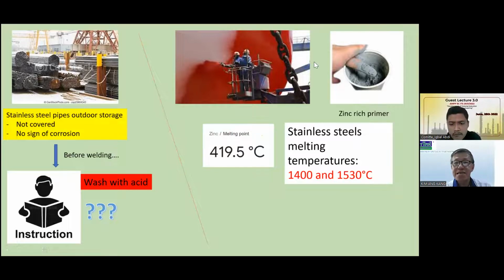Imagine if this zinc dust, zinc dust in the zinc-rich primer, during the spraying outdoor, flew over and deposited on the stainless steel. The deposition of the zinc dust on the stainless steel probably will not cause any problem yet. The problem is waiting. Imagine if we started to weld the stainless steel with the dust on it. What happens to the zinc dust? It means that the zinc dust will melt before it comes to the welding temperature. Probably within the preheat temperature it is already enough for zinc to melt before it comes to the melting temperature of stainless steel. So once the welding of the stainless steel is on, it is time for this zinc dust to turn into liquid zinc.